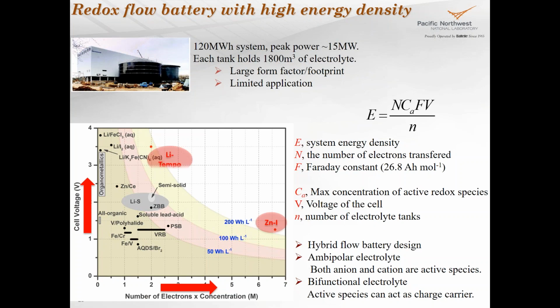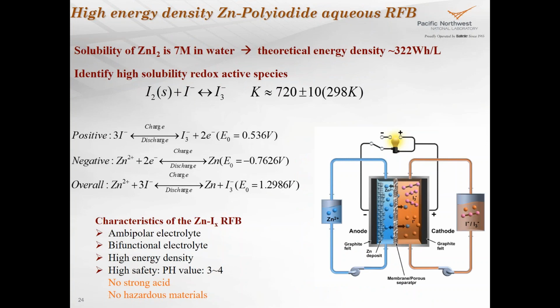We have one system, zinc iodide in an aqueous system, that can go up beyond 200 watt hour per liter, and we also have a non-aqueous system, the lithium Tempo, that can go beyond 200 watt hour per liter. I'll talk about the zinc iodide a little bit. I will not talk about the lithium Tempo due to the time limit. In order to increase the energy density, we have to increase the solubility of the redox active materials in the electrolyte. We know that zinc iodide has a very high solubility, 7 molar, translating to an energy density of more than 300 watt hour per liter. But if we oxidize it to iodine, then it will not dissolve.